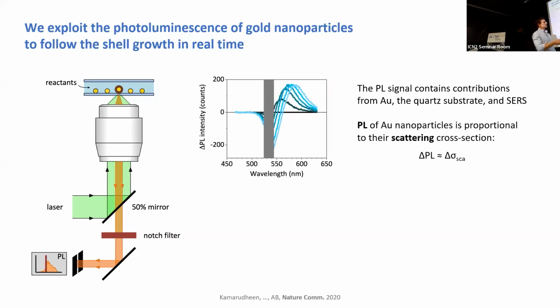And in fact, what turns out is that the photoluminescence of plasmonic nanoparticles scales with the scattering cross-section. Now, if you remember, when you take a nanoparticle and you make it bigger, the plasmon resonance shifts towards the red. And so the scattering is shifting towards the red. And so if you do the delta PL, it should look like a delta plasmon, delta scattering. And that's exactly what we see. This is a positive plasmon resonance minus a negative plasmon resonance. So from the shift in the peak position, we can also tell how fast the nanoparticle is growing a shell around it.